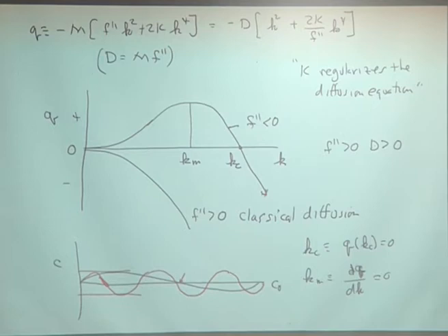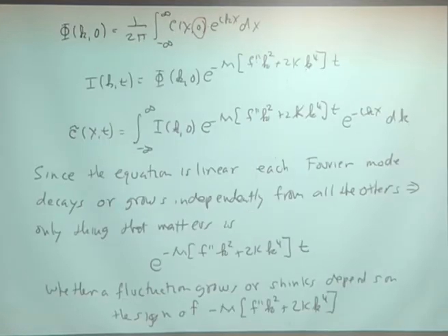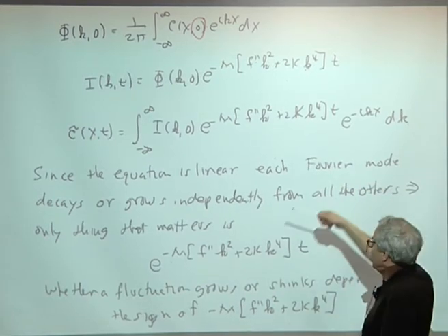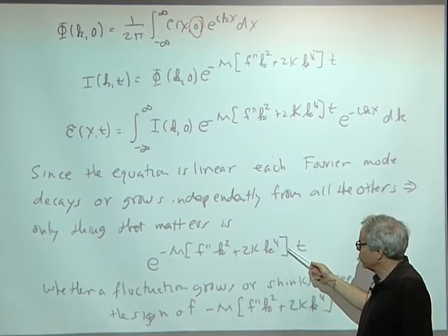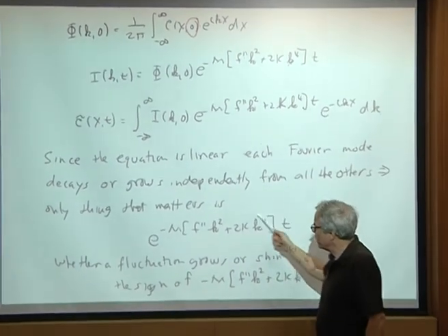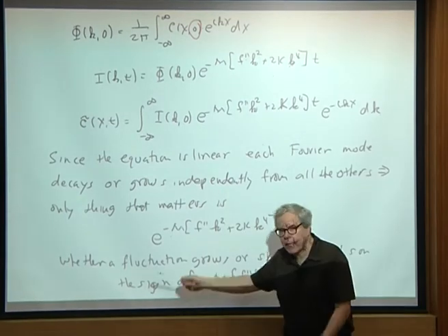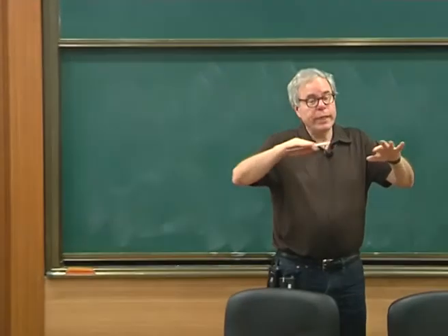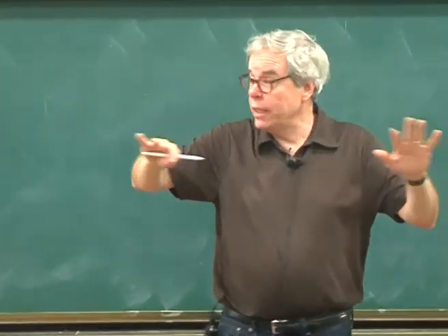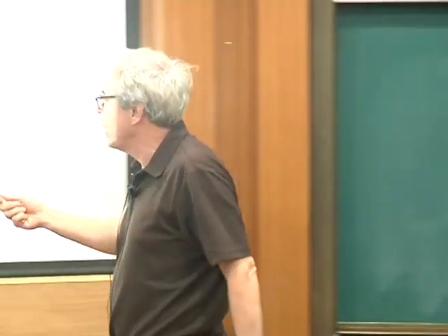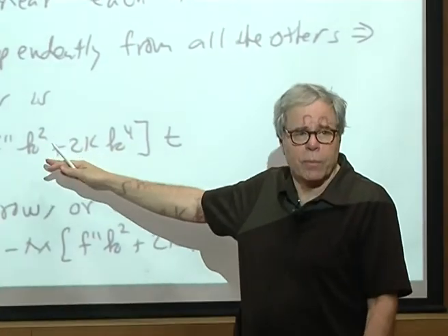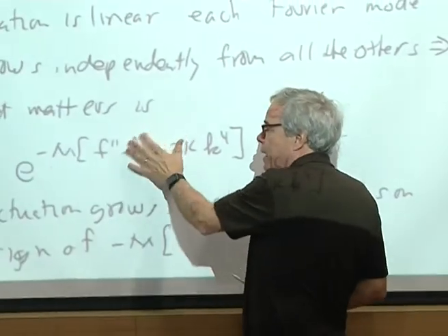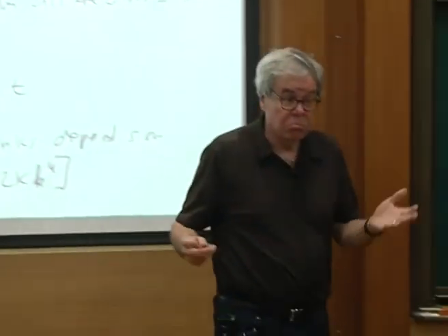And why is the wave number with the maximum growth rate important? Because if you look back here at this equation, it's growing exponentially, right? There's a certain wave vector Km that gives you the maximum growth rate, and it's growing exponentially. So you would expect to see fluctuations in the system that grow, and eventually what you would see is these fluctuations be of the wavelength or wave number Km, because they're growing exponentially, and Km is the thing that maximizes this growth rate Q.